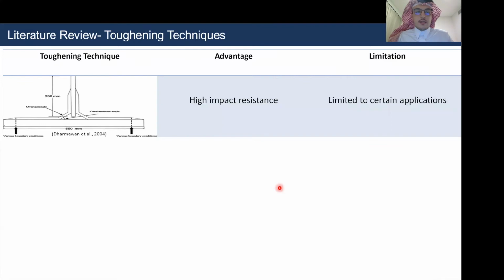Therefore, there are many toughening techniques in the literature. I'll highlight the main ones. So the first toughening technique is modifying the geometry of the T-joint structure. And this can be done by modifying the delta fillet or the curvature region here to improve the impact resistance. So this is mainly applied in marine applications such as boats or naval applications to resist high wave impact. This is only limited though to certain applications where such geometrical modifications are allowed.